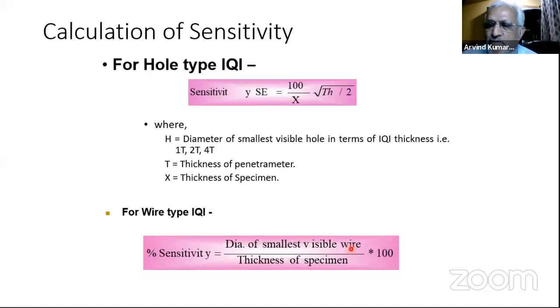So generally, ideally 2% is the acceptable norm. But now the codes have slightly become more practical where, in lower thickness, 2% is difficult to achieve. In a higher thickness, 2% is easy to achieve. So they have made a table where it doesn't talk about 2% or 4%. It says that for this thickness, this should be the wire visible straight away. Oh, sorry, for lower thickness, they accept up to 3.5% sensitivity also because it is difficult to achieve. And for higher thickness, you go for even 1.5 and 1.8.